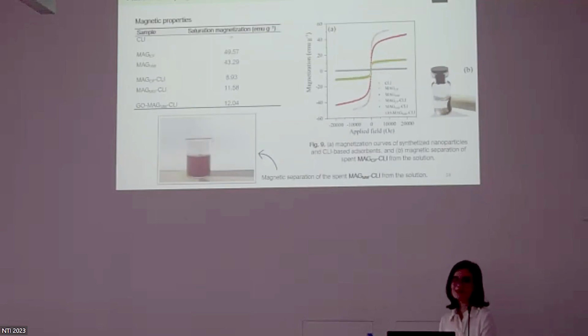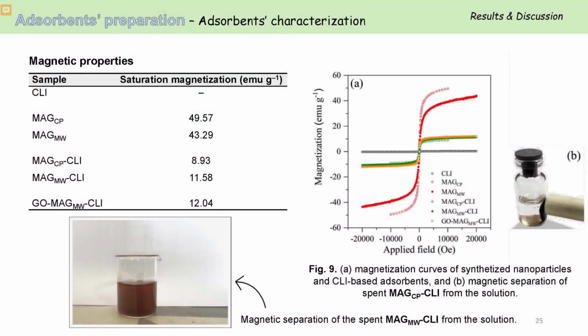Also, the magnetic properties of the synthesized samples were measured and compared with the magnetic properties of the pure magnetic particles. We can see that all samples show similar magnetic behavior, and the saturation magnetization values are listed here in the table. What is important to point out is that coating with magnetic nanoparticles induces magnetism in clinoptilolite, which doesn't have it by itself at the beginning, so that separation of the magnetic clinoptilolite from the solution after the adsorption is possible with an external magnetic field.